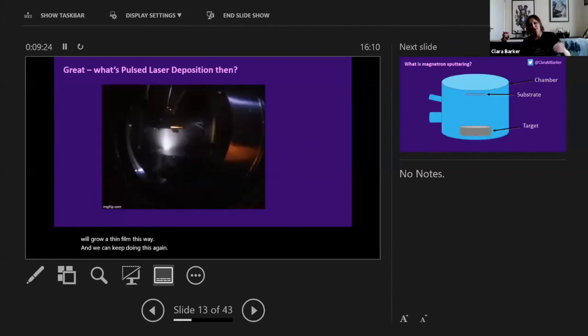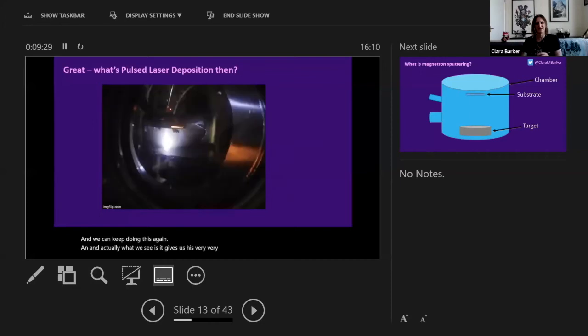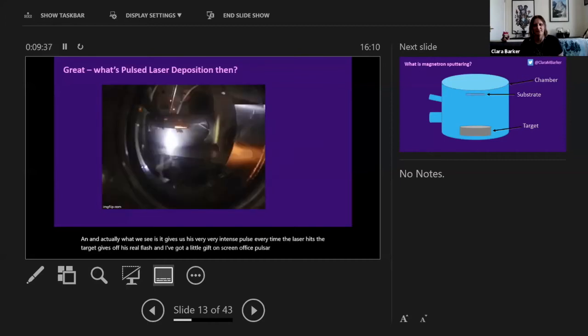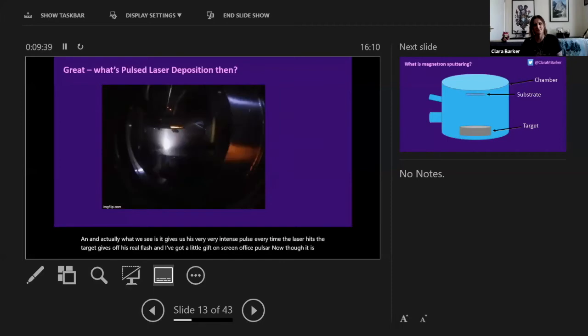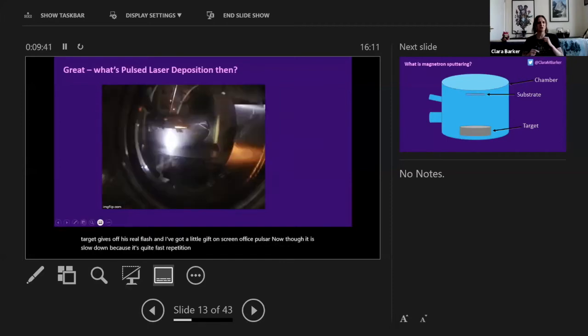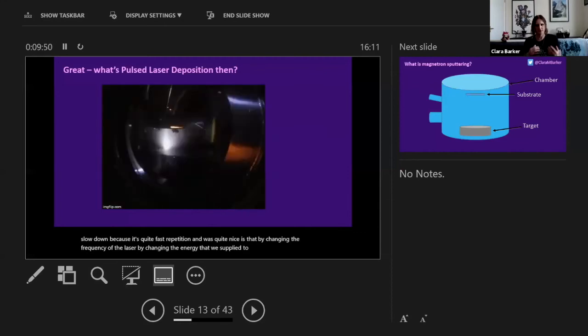What we see is that it gives us this very, very intense pulse. Every time the laser hits the target, it gives off this real flash. I've got a little GIF on screen of this pulsing, although it is slowed down because it's quite a fast repetition. What's quite nice is that by changing the frequency of the laser, by changing the energy that we supply to the laser, we can tune the structure of the thin films that we grow. And it's the same with the background pressure and the background gas and things like that.